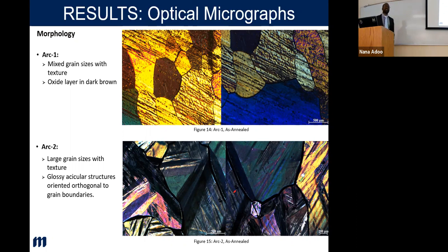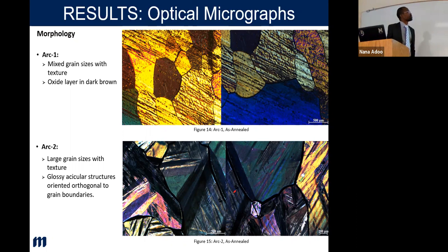the condition of the annealed. And you could see there's enough texture out there for the arc melt 1 and then the 2. And with the 2, you could see some acicular structures which look like martensites. And martensites are actually needle-like. They're strong, they grow orthogonal to grain boundaries. And looking at these, you could also see some features of those things, but this material failed too. So the fact that there was martensites in there did not guarantee a phase transformation.